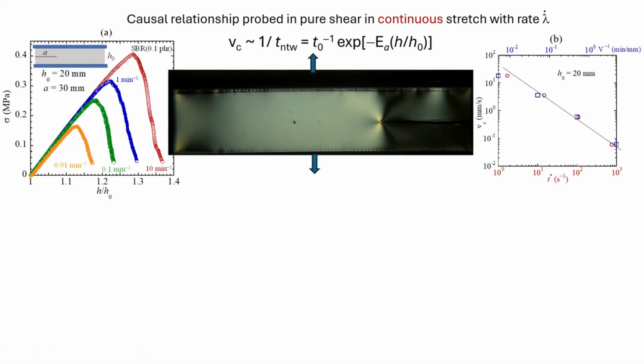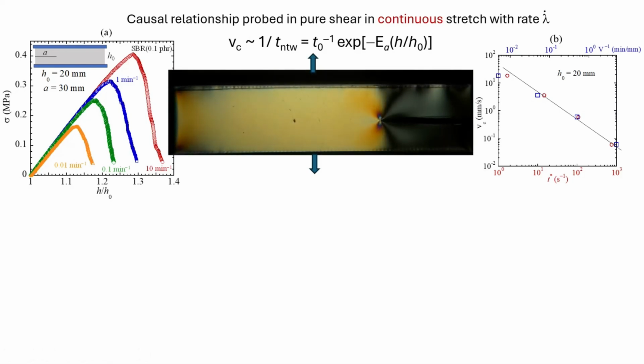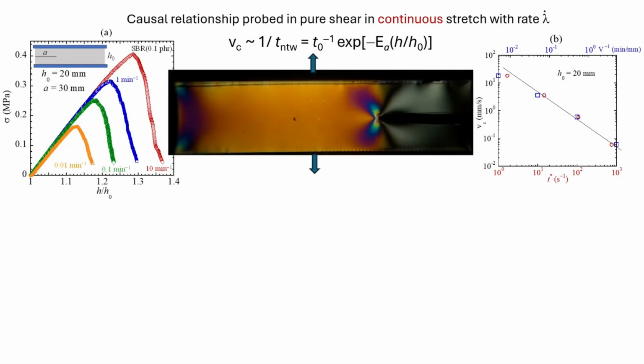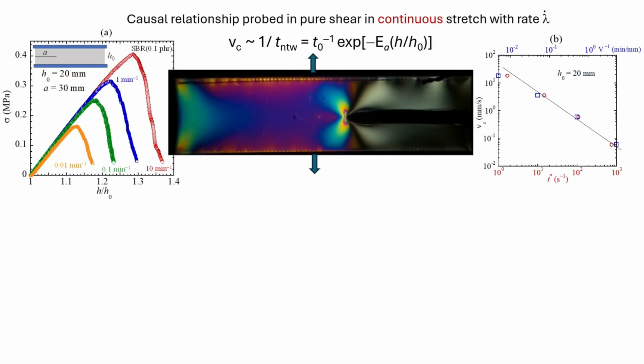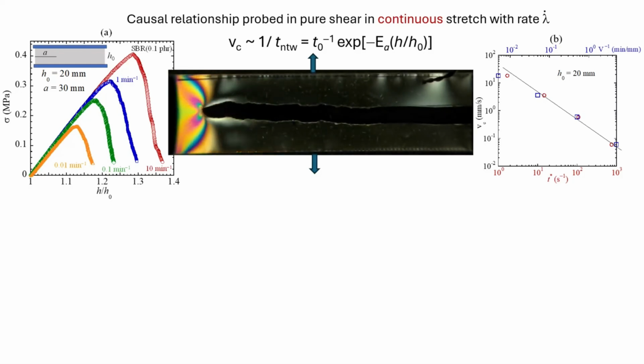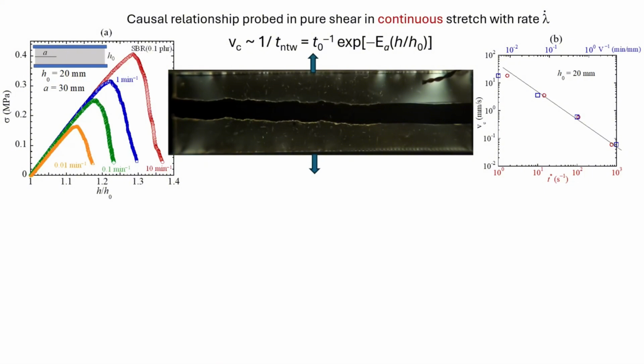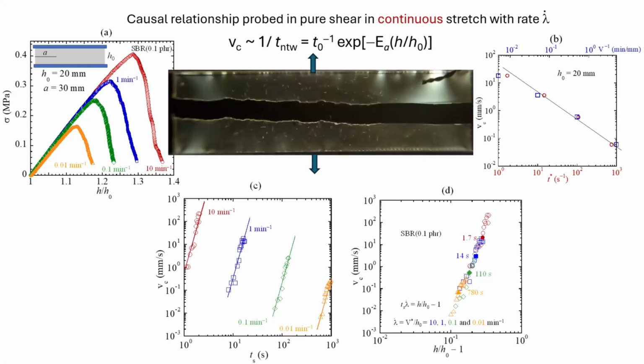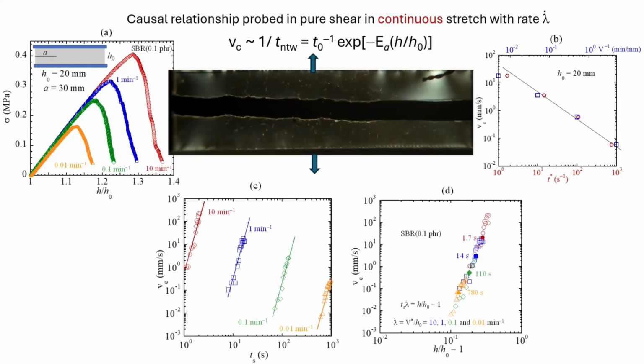Remember I indicated much of the old data used peeling or tearing, so you claim the so-called crack speed. But crack speed is not an essential variable. So the best way is to do an experiment called pure shear. You stretch to different levels and watch at different levels how the propagation speed changes with the load. You find the whole thing is independent of how you're doing it. It only depends on how much you have stretched, in the limit where viscoelasticity does not matter.